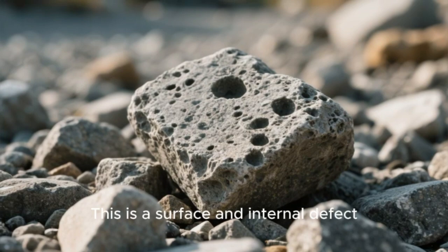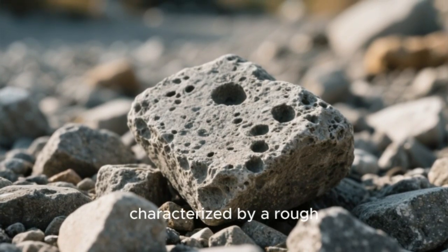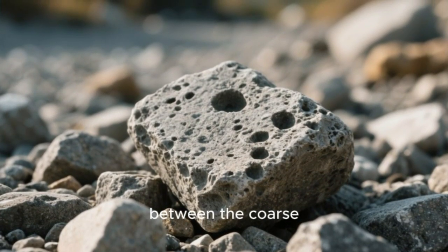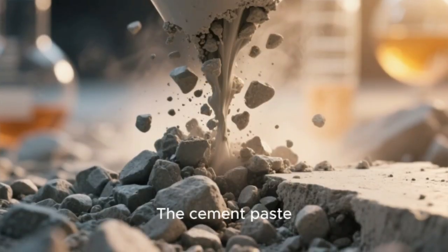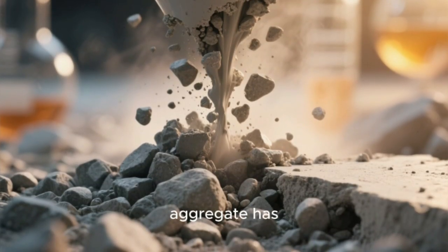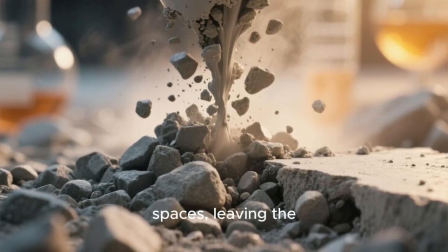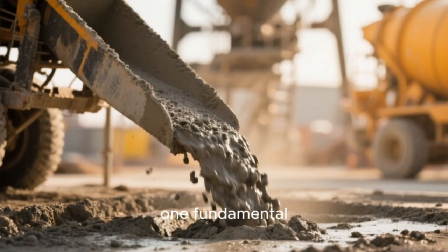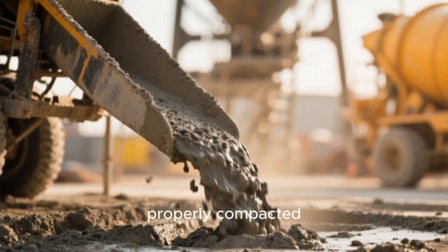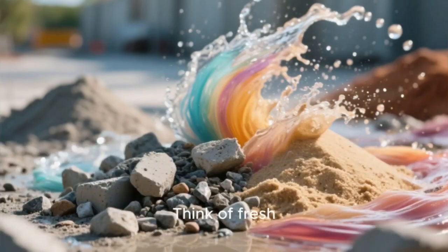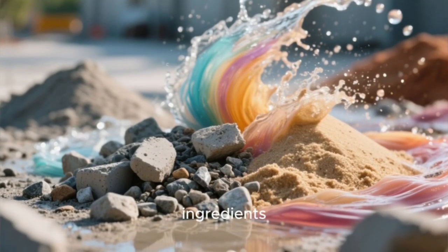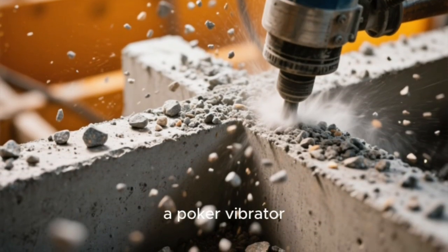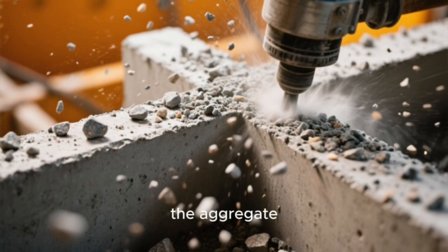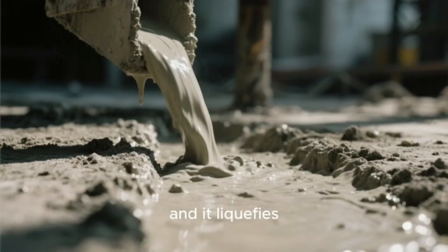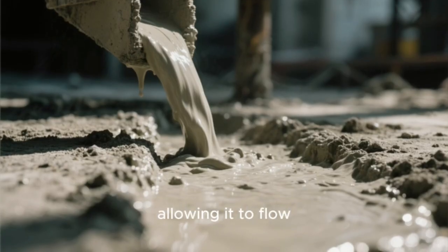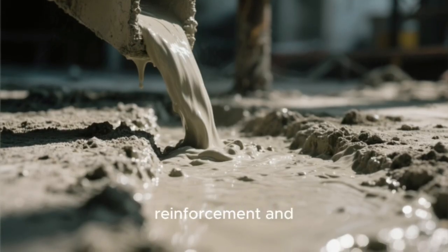This is a surface and internal defect characterized by a rough, stony texture with voids and cavities between the coarse aggregate particles. The cement paste that should envelop and bind the aggregate has failed to fill the spaces, leaving the aggregate exposed. This happens for one fundamental reason: the concrete was not properly compacted to achieve full consolidation. Think of fresh concrete as a complex mixture of ingredients. The vibration from a poker vibrator does two critical things. It pushes the aggregate particles closer together, expelling trapped air, and it liquefies the cement paste, allowing it to flow into all the spaces between the reinforcement and the formwork.